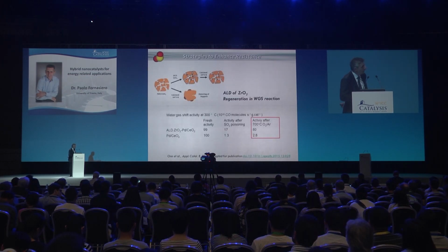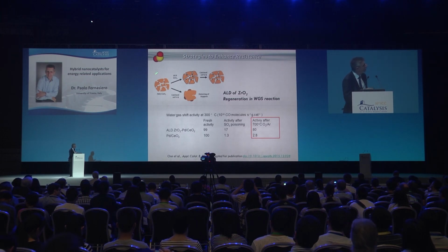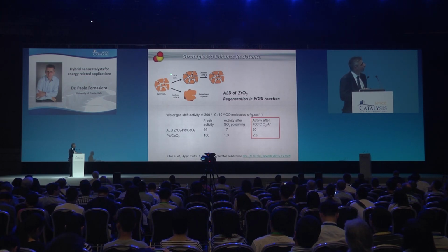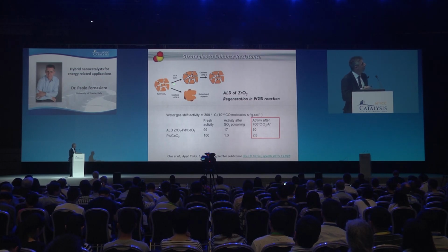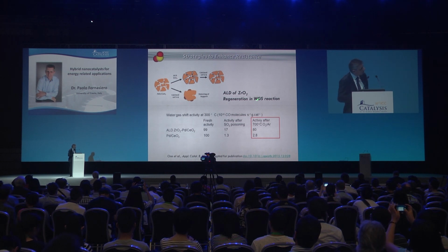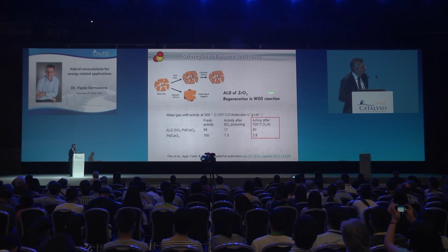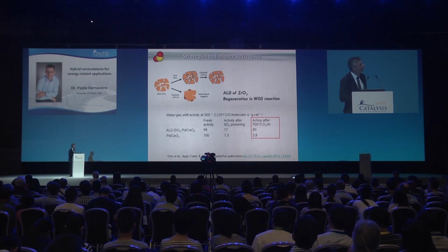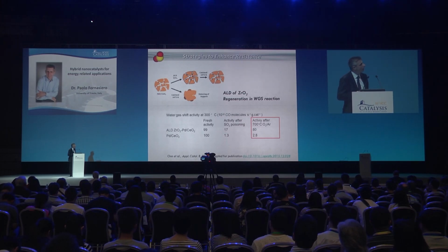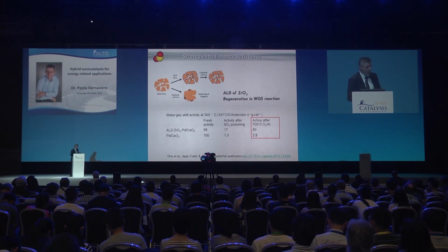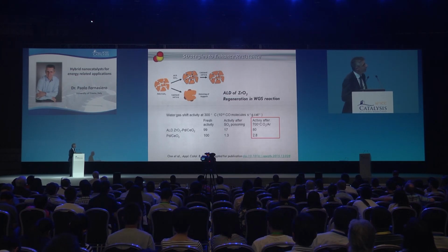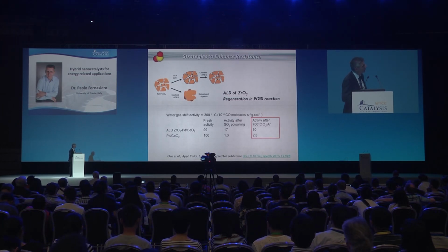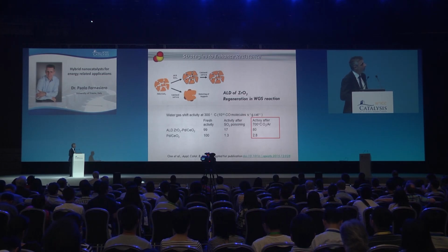So, trying to make the catalyst more resistant in these harsh conditions, we decided to make a test by covering our palladium ceria material with an atomic layer deposition of zirconia. We proved that it's valid for the water gas shift reaction and should be valid also for methane oxidation. And we proved that the sensitivity towards SO2 and water is much less significant. So this opens new perspectives for real application under severe conditions.